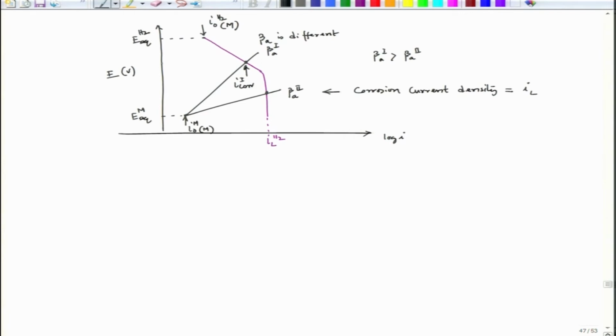So, here this is E mix 1 and this is E mix 2. These are two situations where beta A is different. In this case, I corr equal to I A. Of course, it will be the same as I C of hydrogen, but in this case I C of hydrogen is activation controlled, and in this case IL is concentration controlled.